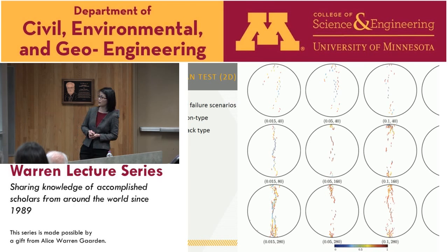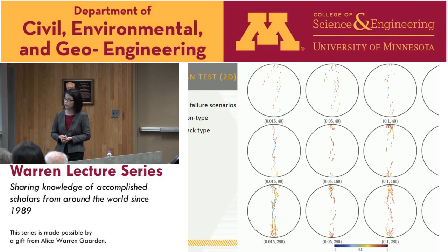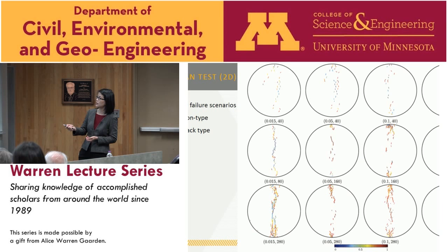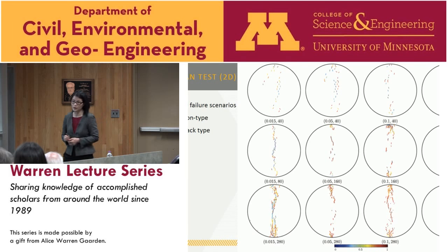And so, in other words, what you can conclude is that if you have elasto-perfect brittle contact laws, you cannot actually produce this center crack type of behavior. Only when you have very low beta, the first parameter over here being beta and the second one being the diameter of the sample in millimeters. Only when you have a low beta, that is a high strength ratio, could you actually observe a tensile crack.